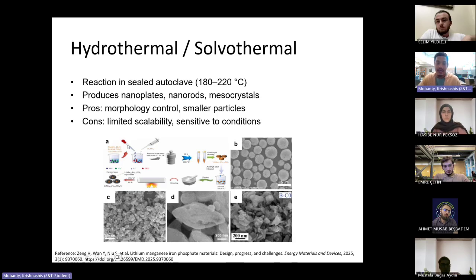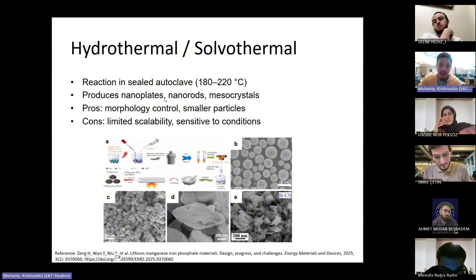Okay, this is quite interesting. I like this method because this is the only method in LMFP synthesis which does not require high temperature, does not require high energy, so it's much more cost effective. We do not need a furnace for this. Our material preparation is quite standard, where we mix stuff and, again, metal salts are dissolved in a solution and then sealed in an autoclave. And the autoclave is put inside an oven.